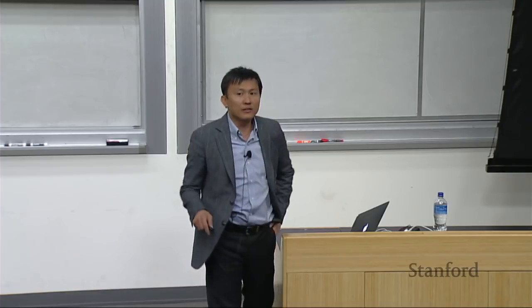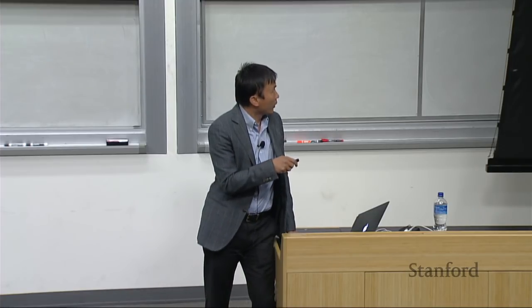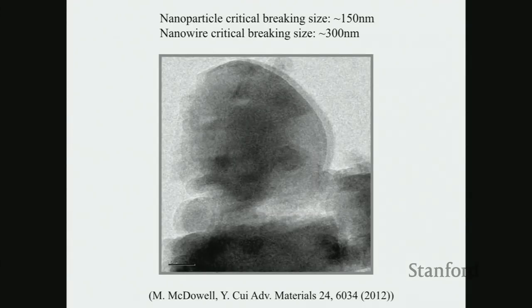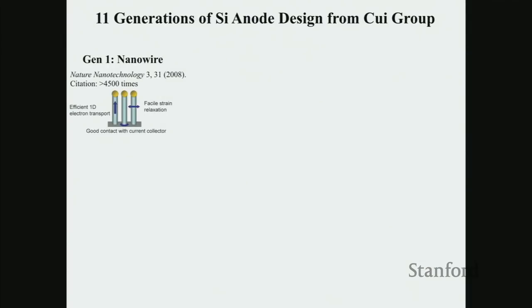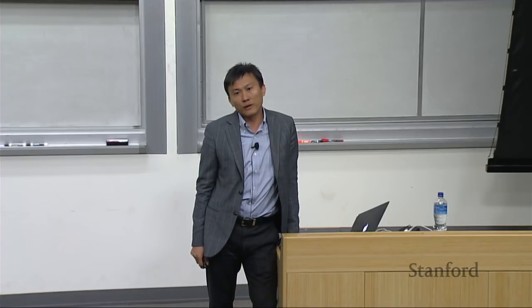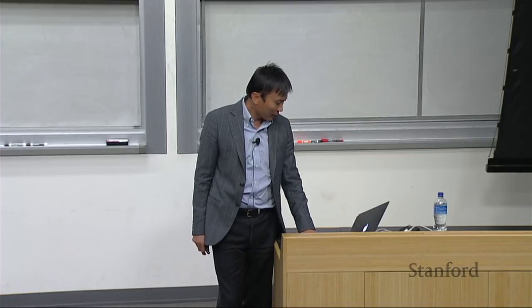So using a technique like this, we could identify the critical breaking size. After the particles are smaller than that size, they won't break anymore. 150 nanometers is about the size. And with this understanding, my group has been through 11 generations of design. This was the first generation. We start from silicon nanowires. They have small diameters, volume expansion can happen, but they don't break anymore. We solved the breaking problem. Indeed, this paper started the whole research field of using nanotechnology for energy storage.